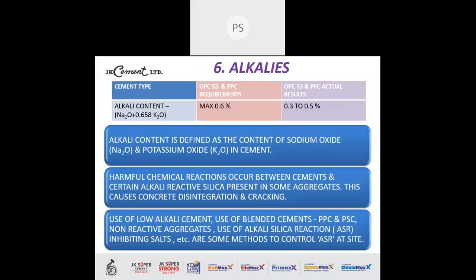Alkali content is defined as the content of sodium oxide, Na2O, and potassium oxide, K2O, in cement. Harmful chemical reactions occur between cement and certain alkali reactive silica present in some aggregates. This causes concrete disintegration and cracking. So for a quality control engineer, especially in high-rise structures, it is very important to investigate whether the aggregates at the site contain reactive silica or not.